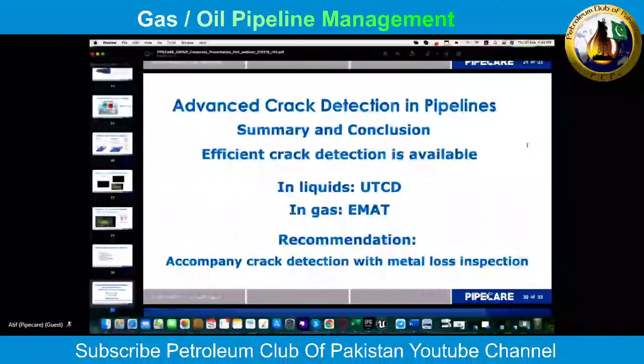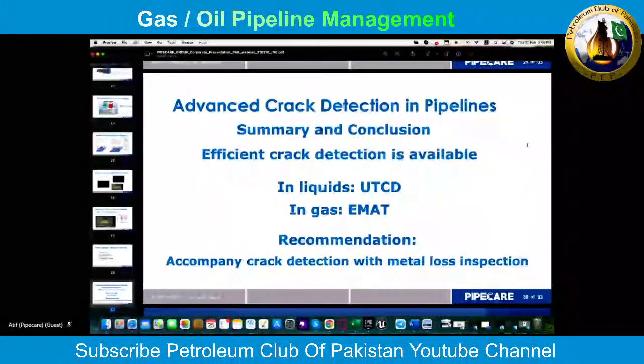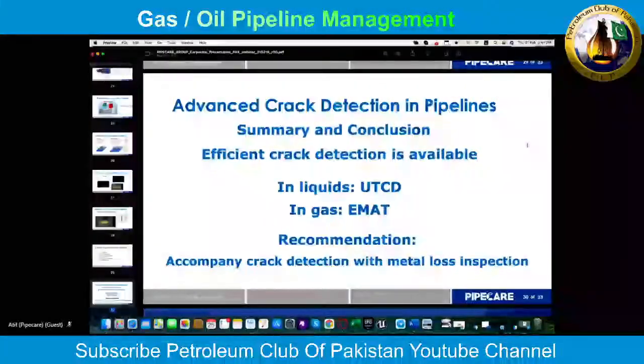And both methods give reliable information on cracks in pipelines, especially on stress corrosion cracking. One recommendation when you are planning to do a crack detection inspection: always make sure that you have a metal loss inspection done either at the same time or not longer than 1 year behind. And this is for a reason.